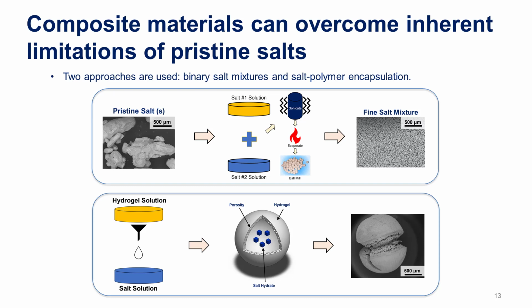And so we're focused on 2 approaches to try and address these inherent limitations that pristine salts have. In the first case, we're making salt mixtures. So we start with our pristine salt. We make a water solution of 1 salt and the second salt, mix the 2 solutions together, evaporate the water, and then ball mill it. And then we get this nice fine salt mixture.